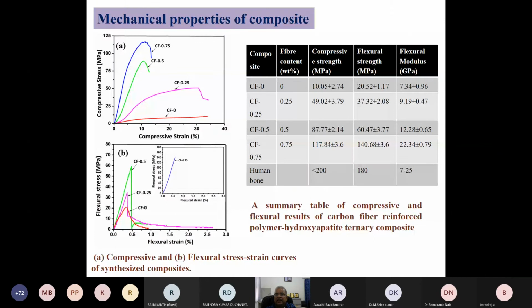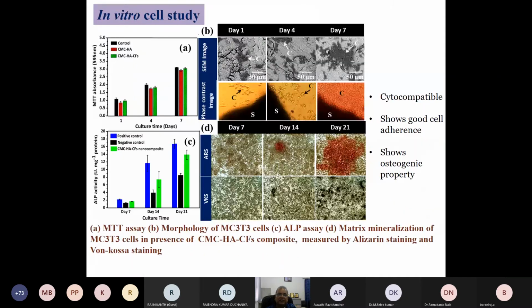And we got the mechanical property, and I am happy that we have reached the flexure modulus of the order of bone with the different carbon fiber. We have got up to 22.34 gigapascal from 7.34 where there was no carbon fiber, then 9.19, 12.28. In the sample where the carbon fiber was high, 0.75 fiber weight percent, we got 22.34, and you see the human bone flexure modulus varies from 7 to 25 gigapascal. So we are very close, and this has been translated.